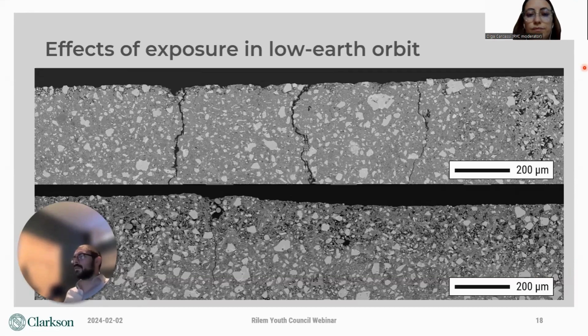They flew the samples back to Earth and we cut them perpendicular to the exposed surface to look at their microstructures. Here you see 2 of those samples, where this black region at the top represents the exposed surface. The top sample experienced significant surface cracking, probably due to thermal cycling. The bottom sample experienced a lot less cracking. The difference here is that the bottom sample was fiber reinforced and the top sample was not. You can see some of the fibers right here. So we know from this that fiber reinforcement is probably going to be a critical part of lunar concrete in order to produce durable lunar structures.